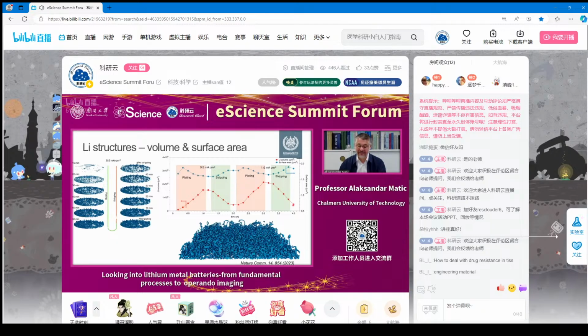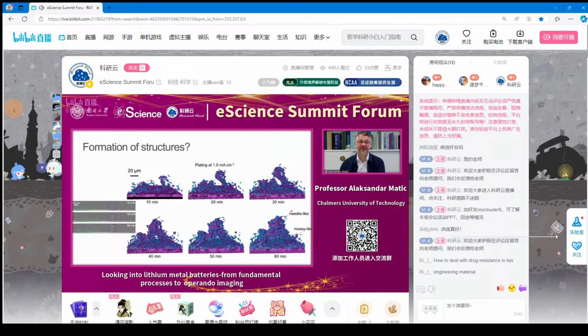What we have here is we could actually also go in and look at the formation of some structures. So in this case, we are following the formation of this very tall structure and seeing how it grows up from the surface, becomes thicker, and in the end, it merges also with growth from other parts of the electrode and forms a very big needle-like structure. But in this experiment, we actually cannot resolve the fine details of the structures growing, because we're limited to this resolution of around 1 micron.